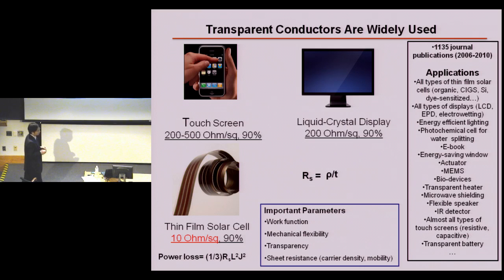And here are examples of the usage of a transparent electrode. So if you have a cell phone with you, the very top layer of your device is actually a transparent conductor. And it depends on the device application and also the device operation mechanism. For example, for voltage dependent devices, such as a touch screen or liquid crystal, basically you are using this transparent electrode to apply a voltage. You don't have a current flowing. So in this kind of structure, the sheet resistance required is about 200 to 500 ohm per square.